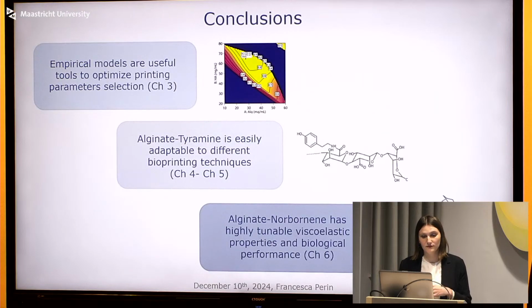So to conclude the overview, this thesis was aimed at finding strategies to try to help translation in the future. And in chapter 3, we found that empirical models were very useful tools to optimize printing without relying on trial and error. Then we tried to build versatile bioinks, and in chapters 4 and 5, we found that alginate tyramine is easily adapted to different bioprinting techniques. However, it still needs a little bit of work on the biological side. And finally, in chapter 6, we found that alginate norbornene was very highly tunable, both in terms of cross-linking kinetics and viscoelastic properties, but also on the biological performance.